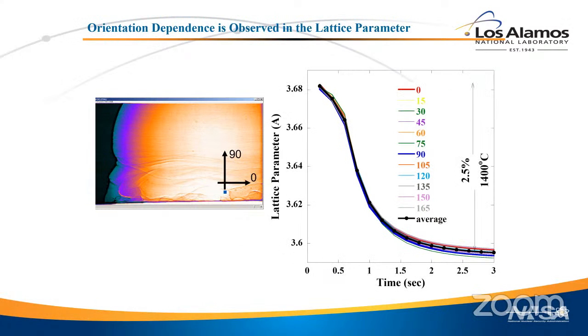Well, here's an example where we actually were fast, probably fast enough. So this is looking at the lattice parameter as a function of time. So not the phase fraction, but the lattice parameter. And you can see that it drops, right? That's just thermal expansion. But also notice that I'm showing you here the average in the thick black and the orientation dependent lattice parameter. So again, this is the difference between the radius of that Debye-Scherrer cone and the eccentricity of that Debye-Scherrer cone.